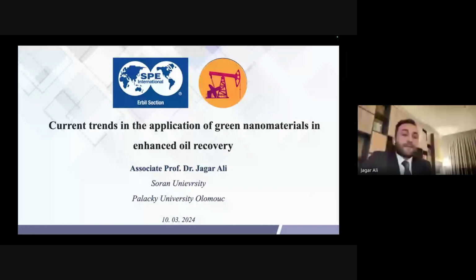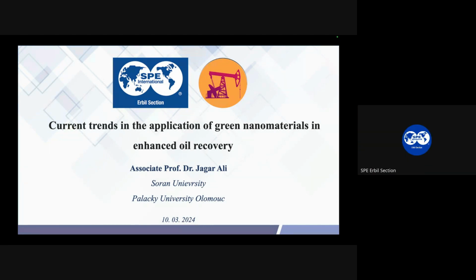And secondly, for dispersion stability, the good way that we use nanocomposites, usually the main idea is to have natural polymers combined with the nanoparticles, and these together will keep the dispersion in a better way. So you should use something with nanoparticles, especially when we use metal nanoparticles. If you use nanoparticles alone, you might have less duration of the dispersion stability. But when you add an emulsifier or some surfactant or polymer, it will keep it for a longer time. Great, many thanks. Liqa Idris, please go ahead.